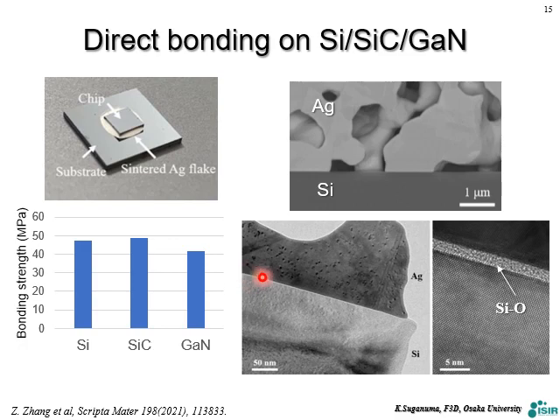And this is showing in TEM, nothing there, but silicon always has a passivation layer like this, very thin, like 1 nanometer or 2 nanometers maybe. So again, in this case, silver is bonded onto the silica layer, amorphous layer. So very interesting.